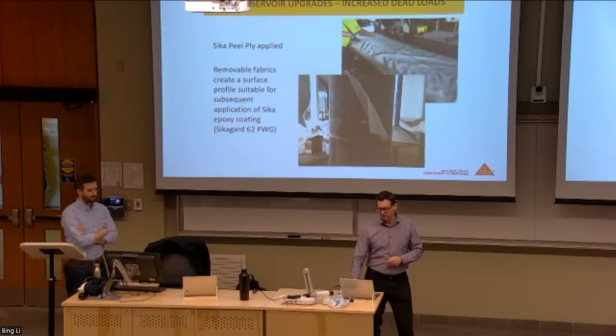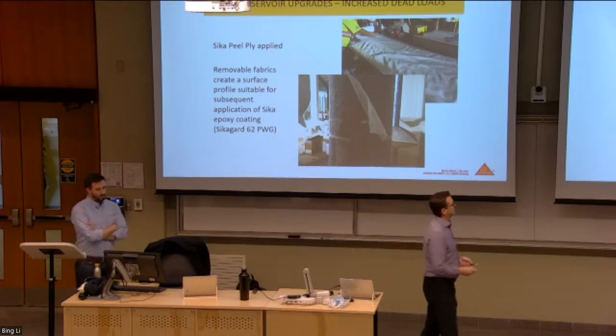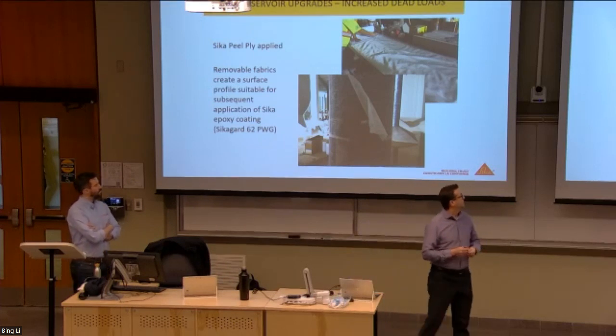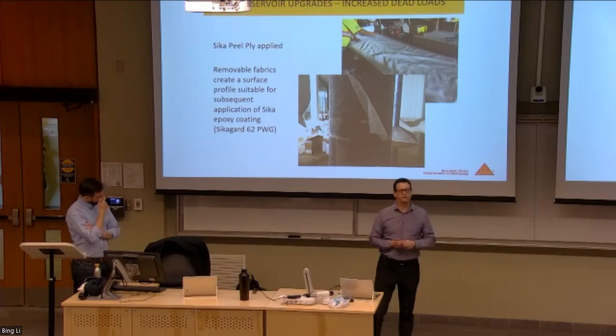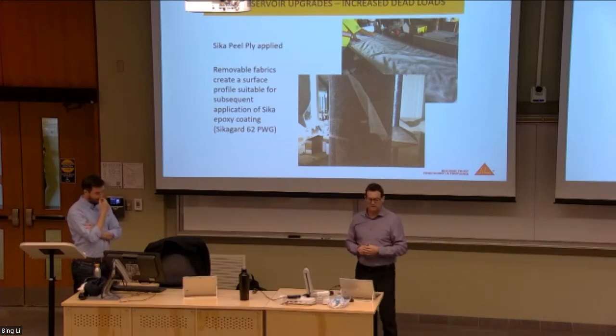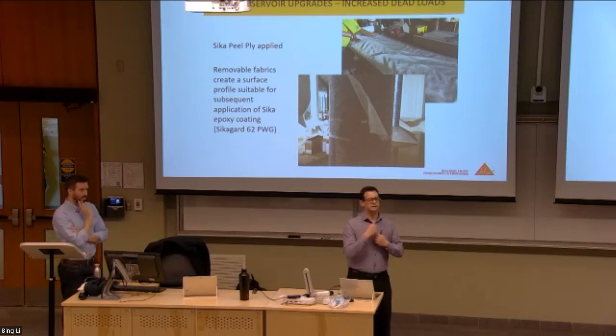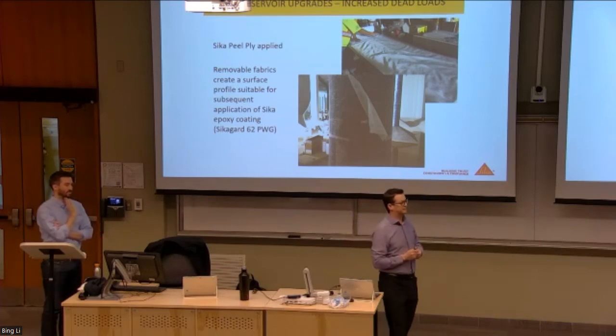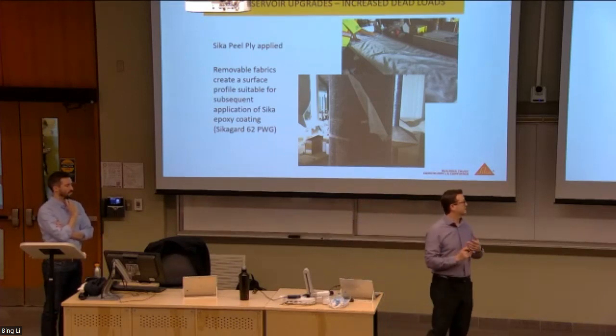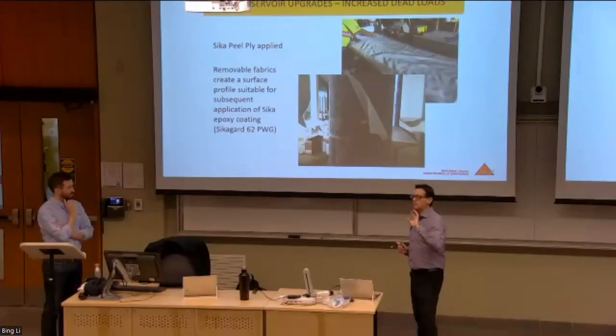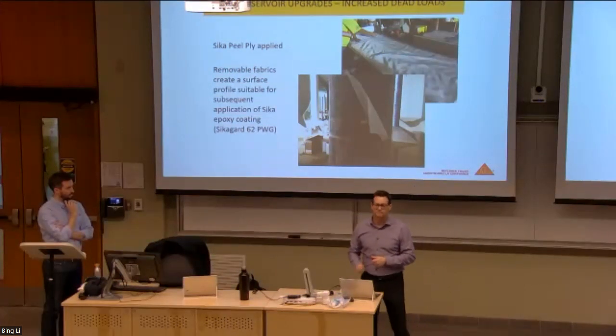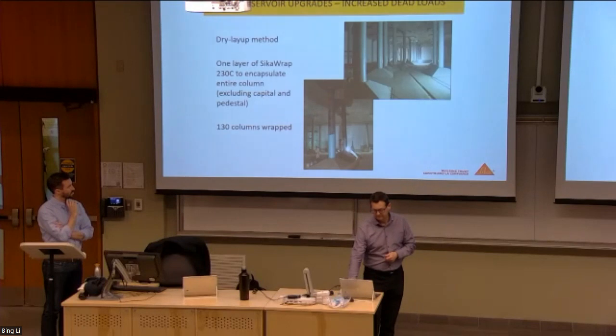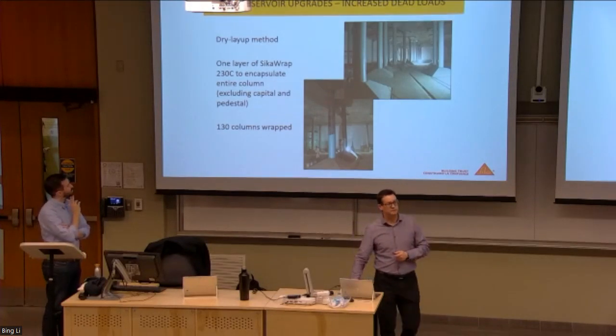Okay, if you wanted to install the coating afterwards, there's a product called peel ply, which can be applied onto the wrap, so that once you take this material off, it facilitates a surface that is conducive to applying an epoxy product over top to get a good bond. And there, that's what we had happen on that epoxy afterwards.